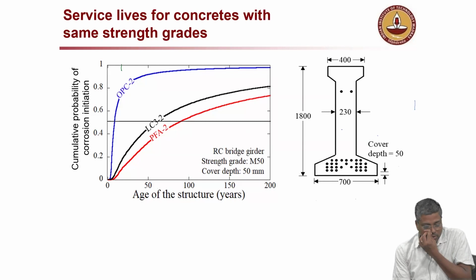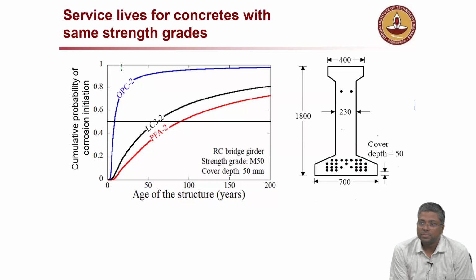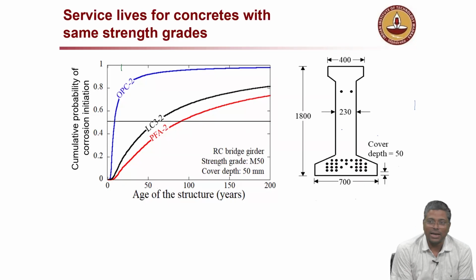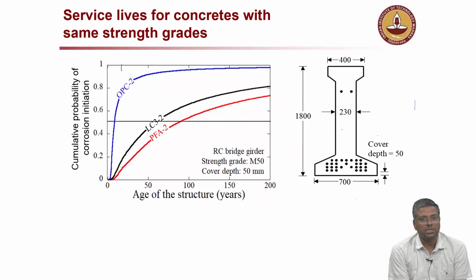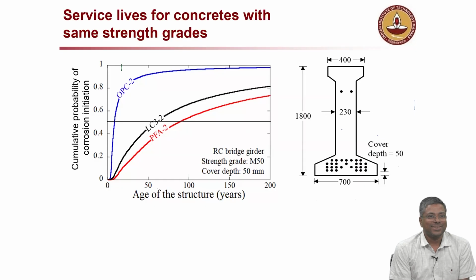Sulfate resistant. Yeah. So what is sulfate resistant cement? What do we change in that cement? If you add slag, definitely all these fly ash, slag, etc., they really improve sulfate resistance. But if you buy sulfate resistant cement, this is essentially a cement with less C3A, because C3A is what reacts with sulfate. So I will not give enough reactant, so my reaction is curtailed there itself. Okay, that's the idea. Anyway, anything which is more compact is good.